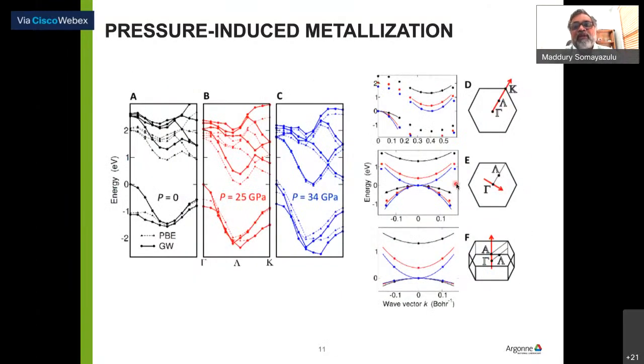And quite simply, what it means is that as you increase the pressure, there is overlap between the bands. In effect, which is shown here in this diagram on the right, what you do is you bring about a metallization just because of the overlap of the conduction and the valence bands.